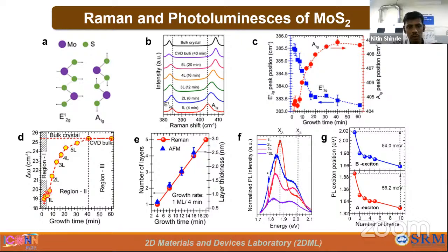This means we can control our growth using CVD. We can also control the number of layers. This is a monolayer, and we confirm it with the atomic force microscope. We are getting results exactly correlated. Then we also analyze PL spectra.